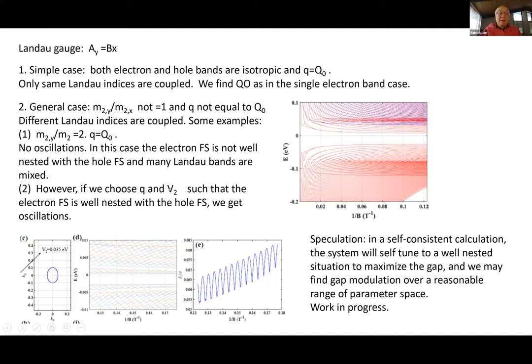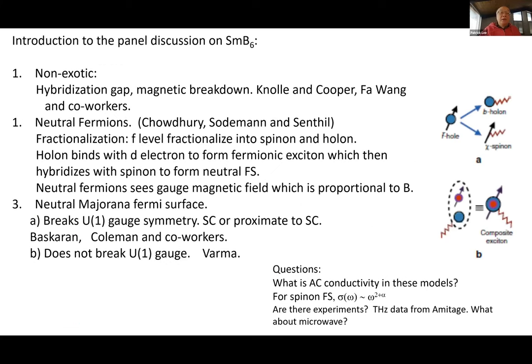He took a Landau gauge. Let me tell you where we are at the moment. In the simplest case, if both electron and hole are isotropic and we can shift so that q equals q₀, this maps back to the original problem and you find quantum oscillations. In the general case we have an anisotropic hole pocket and more or less isotropic electron pocket. If we shift q equal to q₀, then all the Landau indices are coupled and we don't get quantum oscillations—it's almost flat. On the other hand, if you can fine tune the q and the V₀ so the electron pocket after hybridization has good nesting with the hole, then again you get nice quantum oscillation.